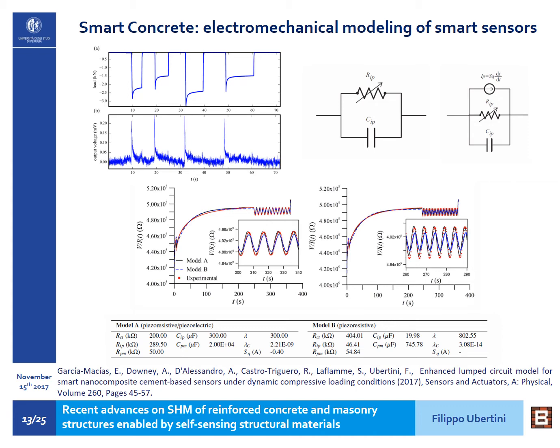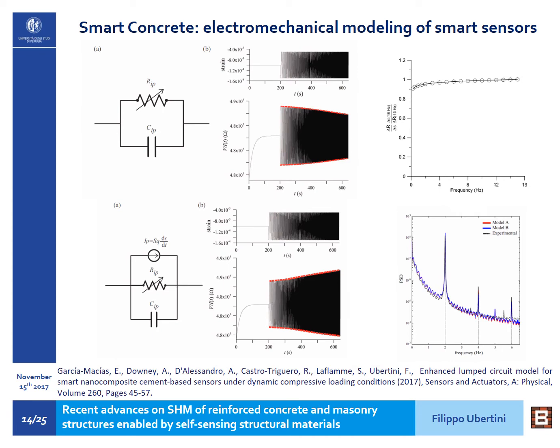We have shown in previous work that with this improved model we can better reproduce experimental results relating to the response of the sensor under application of a mechanical loading of different frequency. But most of all, this model is able to reproduce the possible increase in the amplitude of the response with increasing frequency of the mechanical load. So essentially, the previous, simpler model on the top is associated to a response whose amplitude decreases with increasing mechanical frequency of the load. Instead, if we introduce some piezoelectric behavior of the sensor, we can achieve an amplitude of the response that increases with increasing frequency of the load, which sometimes we observe in the experiments.